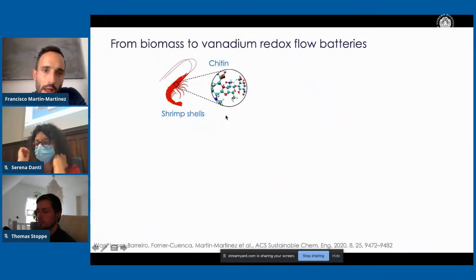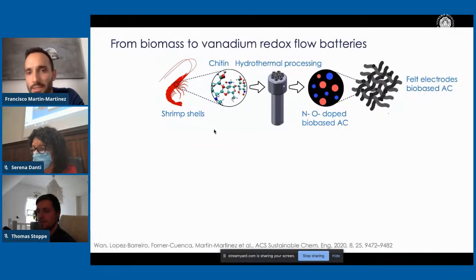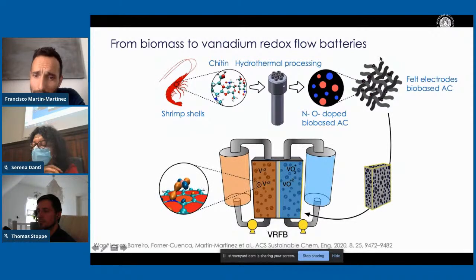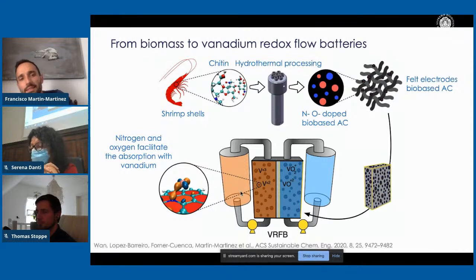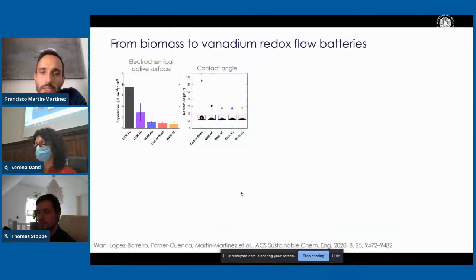So just as an example, by using chitin from shrimp shells and doing this hydrothermal processing, we can create a nitrogen and oxygen doped bio-based carbon, of course with nitrogen and oxygen coming from the original chitin. This carbon we use to decorate some felt electrodes, and then apply those felt electrodes in vanadium redox flow batteries. Basically, what we see is that this nitrogen and oxygen facilitate the absorption of vanadium, and that actually improves also the kinetics.